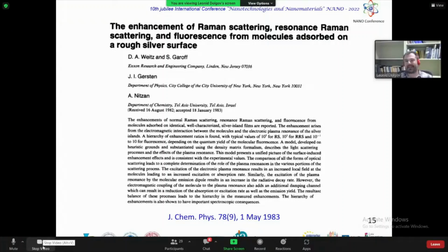And another point is that excitation and emission levels should not be very strongly separated. It works better for organic fluorophores, because for inorganic fluorophores you have a large Stokes shift, and if your plasmon is coupled with excitation, it will be almost not coupled with emission. Therefore, it's desirable to have coupling with excitation, and the emission should not be so far from the excitation.